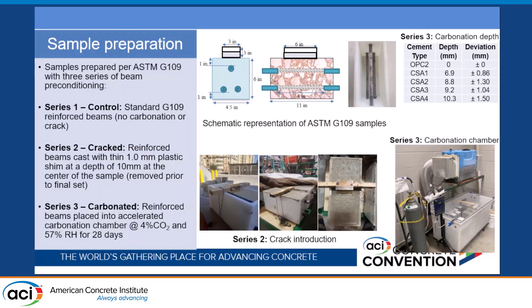In series three, we exposed the samples to accelerated carbonation at 4% CO₂ and 57% relative humidity. The image here shows the chamber in which the samples were exposed to accelerated carbonation. I want to briefly show the results of carbonation that were acquired prior to the measurement of corrosion and chloride ion.